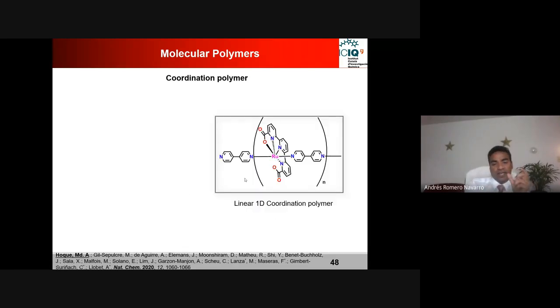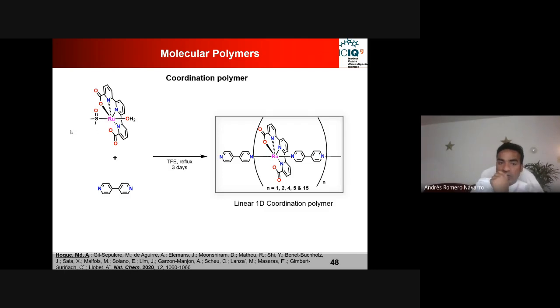So we thought of designing a coordination polymer. If we make a coordination polymer, then we can incorporate more than one active center into that system. So with that purpose in mind, we designed a coordination polymer, taking this ruthenium TDA, terpyridine dicarboxylate, the ligand framework that is known for doing this best catalysis, but changing the axial ligand to some kind of bridging ligand and then trying to make the polymer. And that is what I basically did.